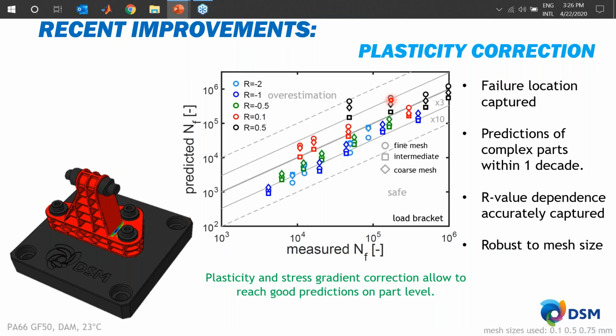And the nice thing is that this approach using the gradient and plasticity is also robust to mesh size. So here you can see the results for 3 different mesh sizes, all consistent in all cases, which is also convenient. So it doesn't mean that you have to recalibrate the model when you start changing the mesh density.